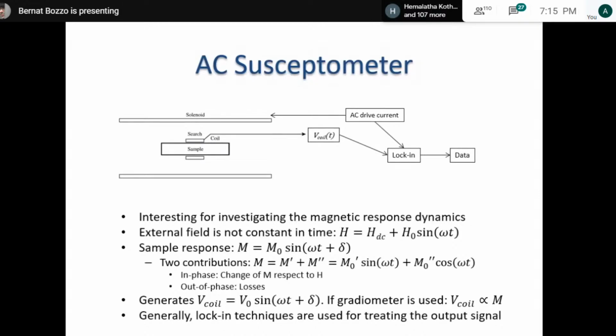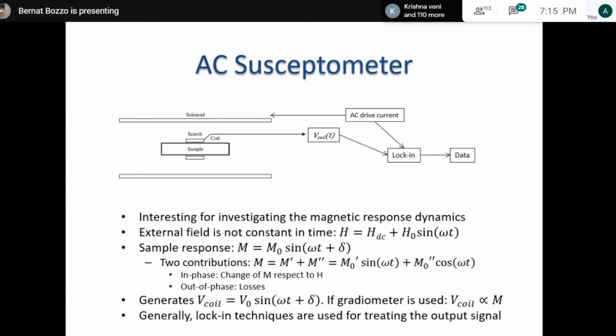Normally, this is useful for detecting some magnetic phase change at a certain temperature, for example. When you have a phase change, we usually have some energy losses involved. So at the end, you have this delay effect that you can effectively measure. Basically, this time-variable magnetization would cause the generation of a voltage at the pickup coils that would be proportional to the magnetization of the sample if we do the proper calibration. Since we are using time-dependent signals, we need some lock-in techniques to filter out the signal we want with respect to the parasitic signals which disturb the accuracy of our measurements.